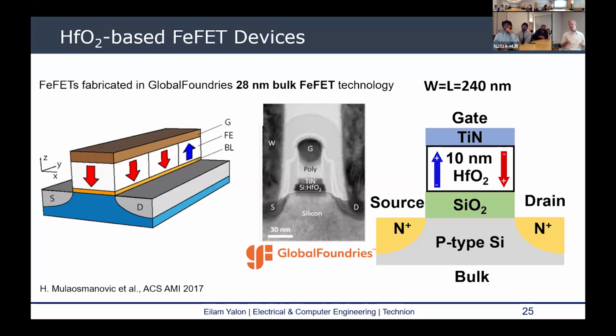And of course, there's some activation energy associated with it. Otherwise, you wouldn't have any retention, right? Because they will diffuse back as soon as we remove the bias. So there are some complexities here, which we don't have the details of. We have some simplified TCAD models to capture the behavior, but we don't really know, and it's very difficult to do this type of characterization. But the encouraging part is that it works.